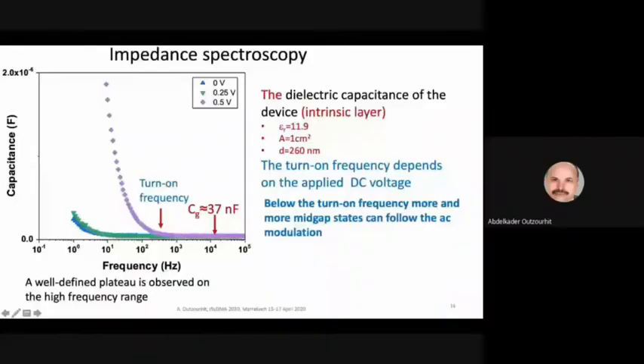Where we present the capacitance of the device in the dark, of course, as a function of the measurement frequency. As you can see, the capacitance decreases and then stabilizes in a well-defined plateau, with a capacitance of about 37 nanofarads. Okay, and a simple calculation of the capacitance of the intrinsic layer, what we call the geometric capacitance or the dielectric capacitance of the cell, is in good agreement with this experimental value here. So this contribution is only the geometric capacitance or the capacitance of the intrinsic layer.